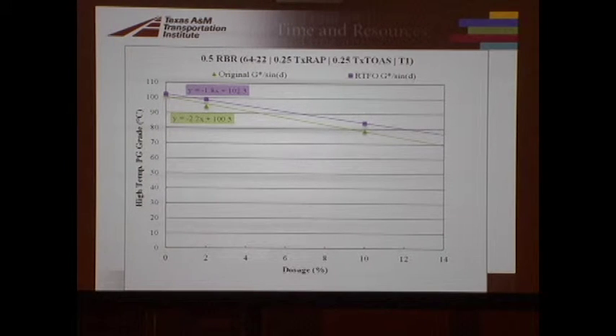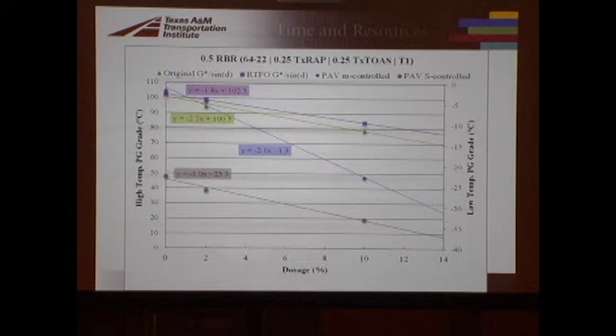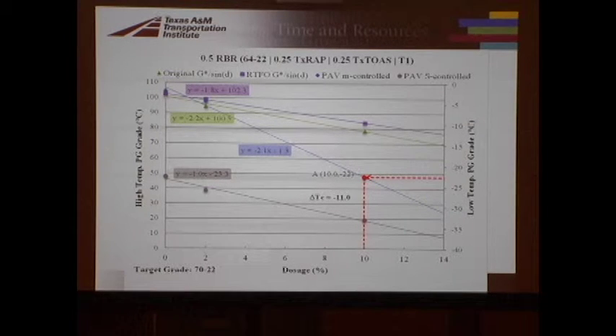Now, what if we try it at one of those high RBRs, 0.5 RBR with a really high RAS content, 0.25 RAS content. Okay, so we get all 4 of our lines. You see the crazy M value line, right? But you do see that it's closing in to the S value line. The delta TC is getting smaller. So the first thing we do is we come along this very steep blue line and we restore to a minus 22. So once we get to a minus 22, that's at a dosage of 10%, okay, and a delta TC of minus 11, which seems high.